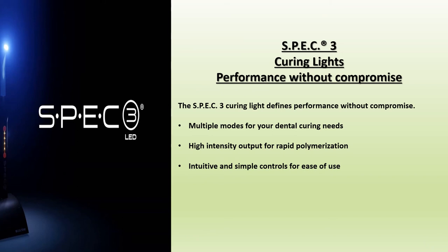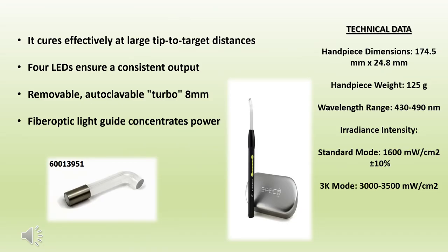The SPEC 3 curing light defines performance without compromise. It has multiple modes setting and high intensity output, that is 1600 milliwatt per centimeter square for standard mode and 3000 to 3500 milliwatt per centimeter square for 3K mode. It reduces the chair time because it facilitates rapid and deep polymerization of various light cured materials. It has four LEDs to ensure a consistent output and a removable turbo tip. It also has a fiber optic light guide.